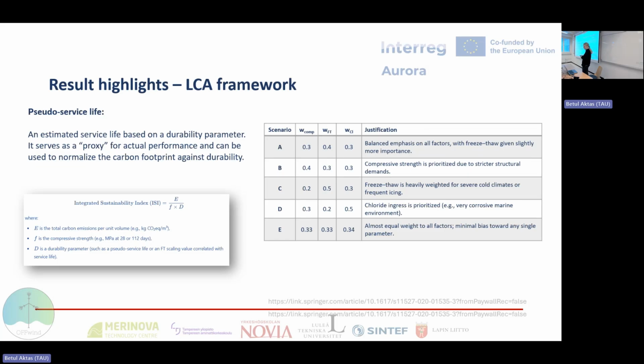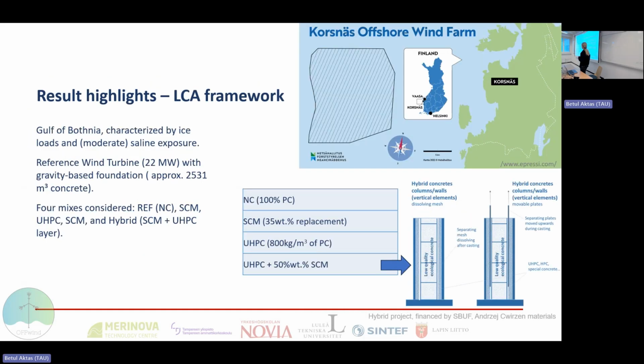So regarding the durability framework, as I mentioned, the majority of LCA calculations that you can find in literature still focus on the cradle to gate approach. So what we wanted to do here is to try to make a very simple parameter that we can use to assess different low carbon solutions for offshore concrete foundations, including the durability parameters that we need in this case. So the freeze and thaw performance and chloride resistance, and also strength, taking into account different scenarios with different weights to see what are the results of their carbon emissions in those situations.